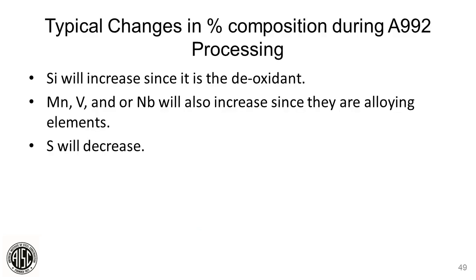All right, so here we go, typical changes in the composition during A992 processing, again the standard wide flange grade that we make the most of. Like we talked about on the previous slide, the silicon will increase since we're trying to get the oxygen out, so we add silicon to remove oxygen. Manganese, vanadium, and niobium are also added to be increased, and sulfur will decrease as we process the heat. Next slide.